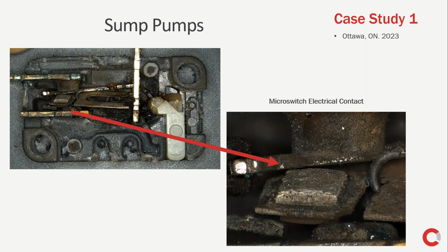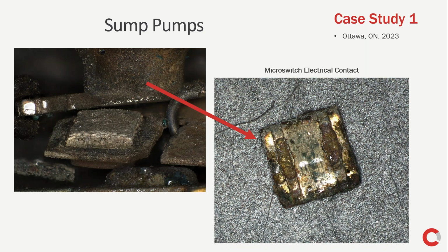And this basically tells us that one of the pads disconnected or was not properly attached to begin with and came off. Obviously, if you have a loose metallic component in a system like this, then it's most likely going to contact something and create a short circuit. And that's most likely what happened here. We did find the missing pad. It's here. This is the back side where it was supposed to be welded to the tab. And again, in this case, it was clearly a manufacturing issue.